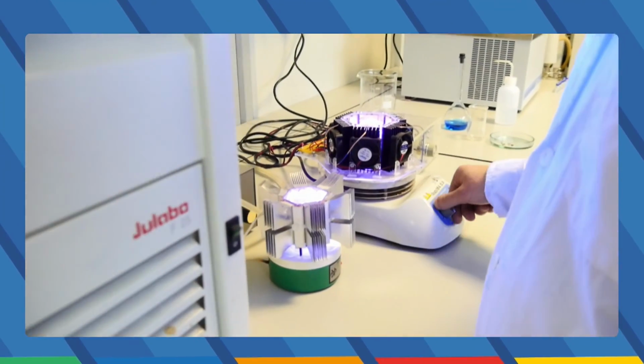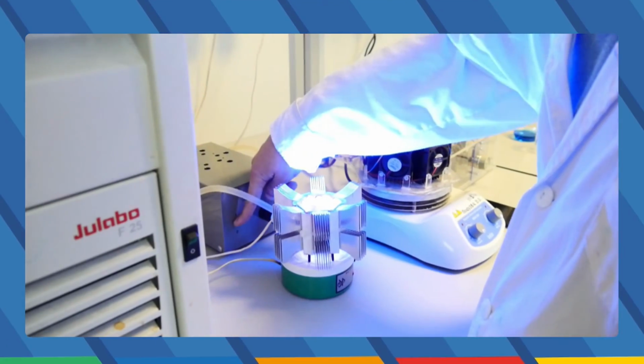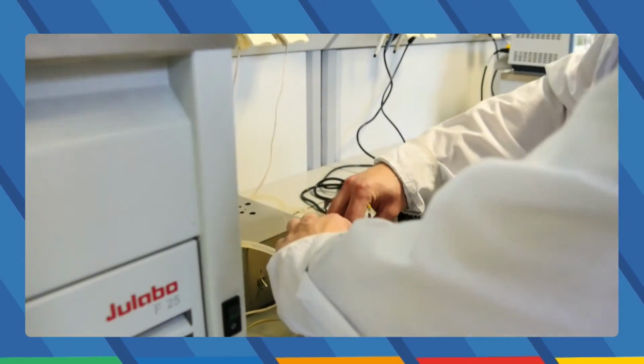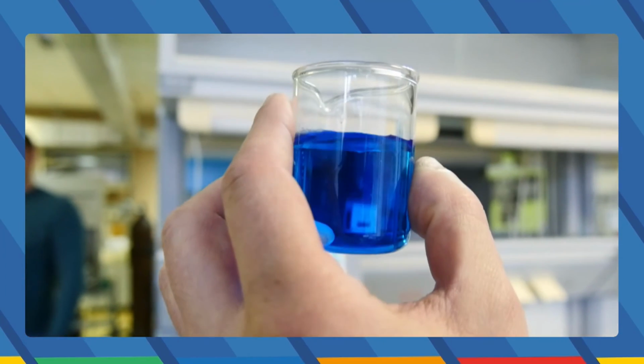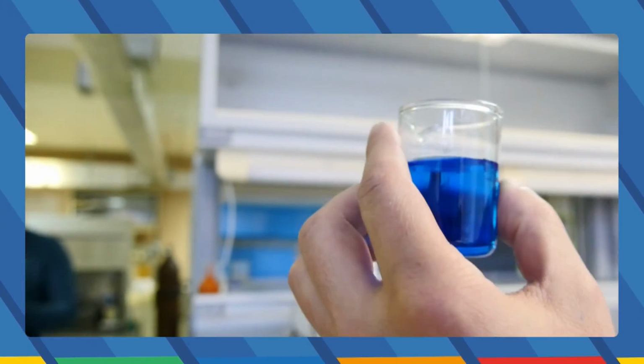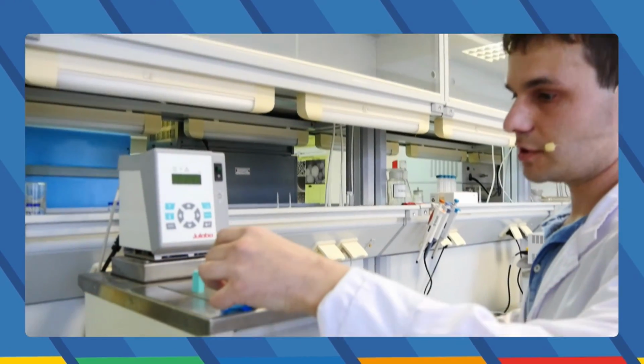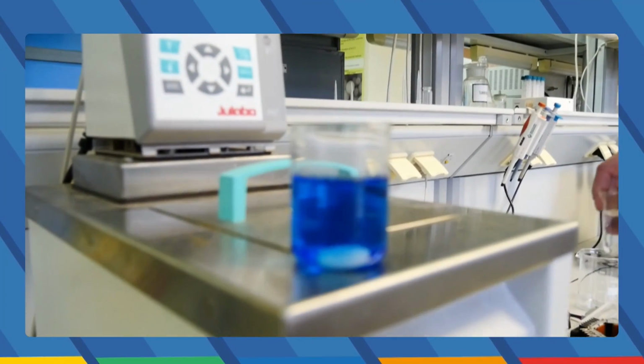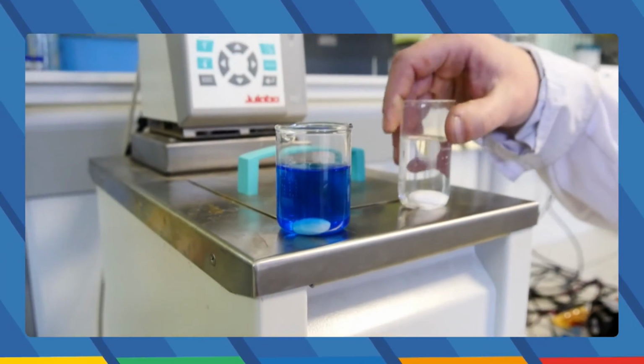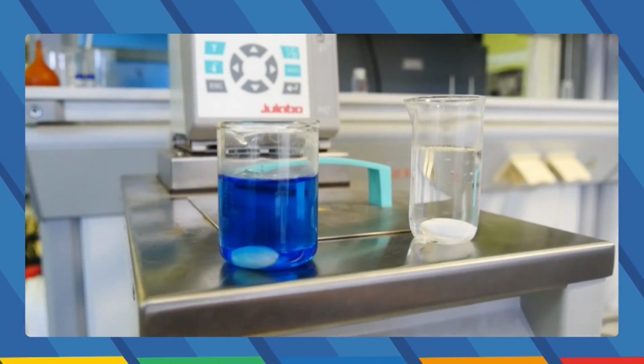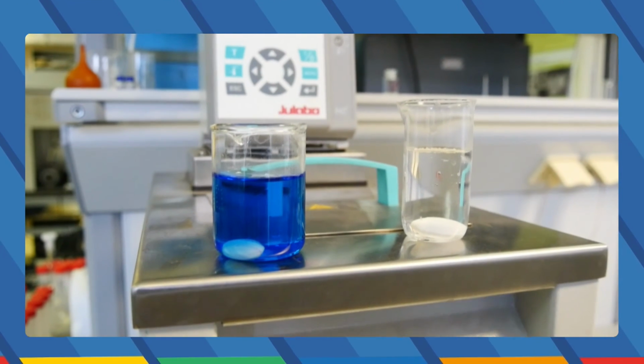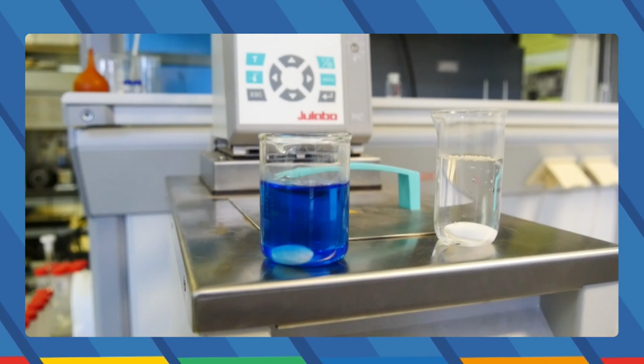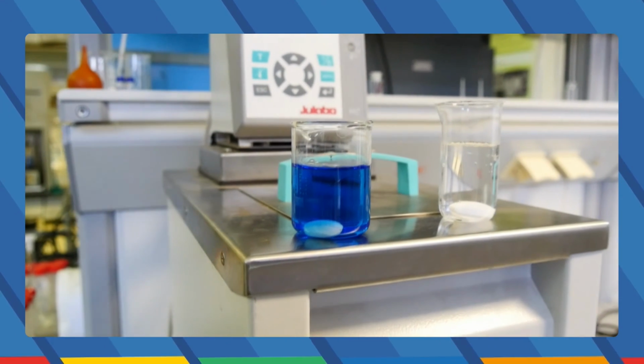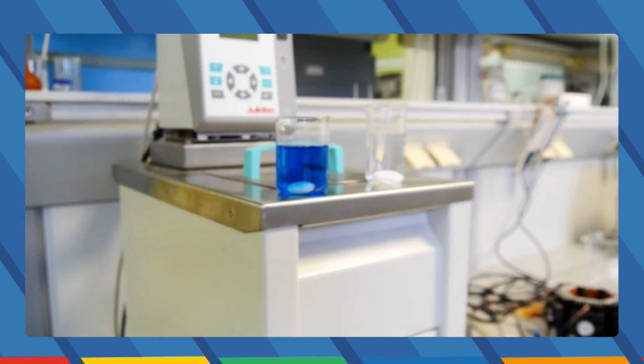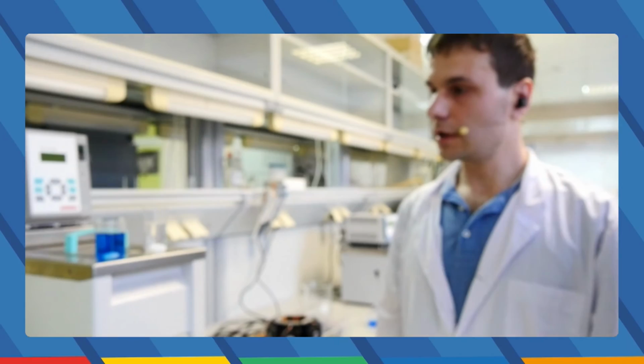and so firstly we can see this material, which has no photocatalyst, and we can see that this material retains its color, blue color of methylene blue dye. So another glass contains the solution with our photocatalyst. As we can see, during this short time, methylene blue dye was completely degraded to water and carbon dioxide.